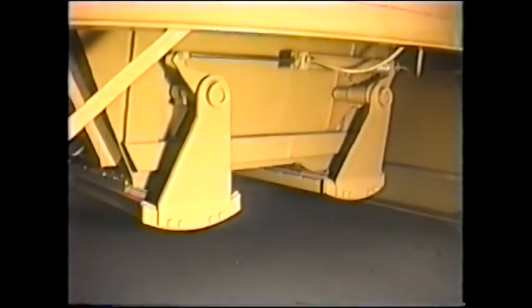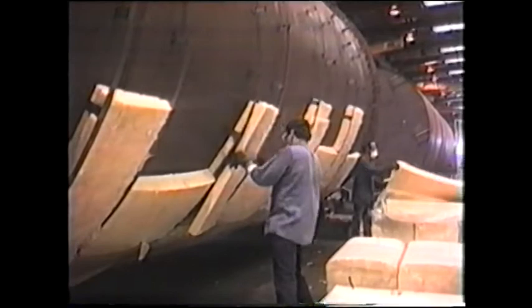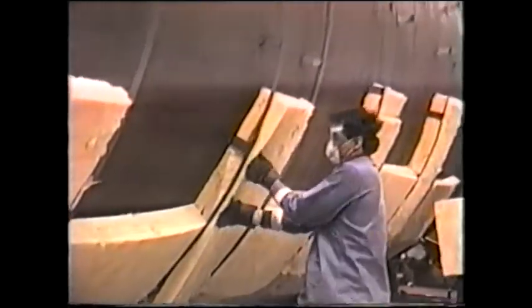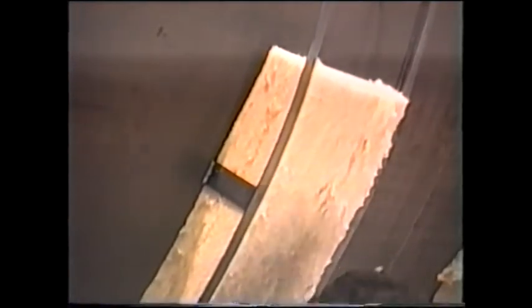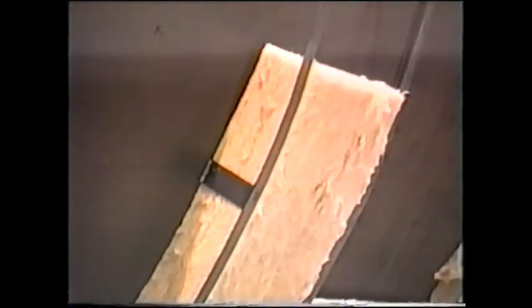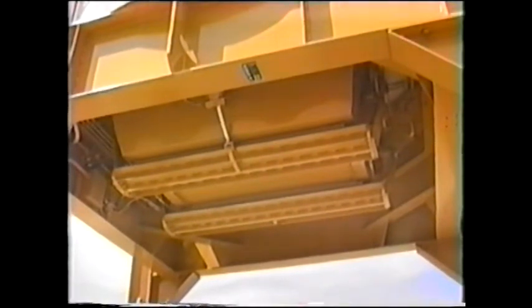At the bottom of the silo, clam gates swing outward to open and inward to close. They are also mounted on cam assemblies and pulled upward to initiate an airtight seal. The optional inert gas generator effectively removes all oxygen. Temperature of the stored mix is also very important. In the EMS silos, walls contain 5-inch thick super heavy-duty insulation with an R value of 21.7, the highest in the industry. The top of the silo has 10 inches of insulation, and the bottom cone is heated with circulating hot oil.